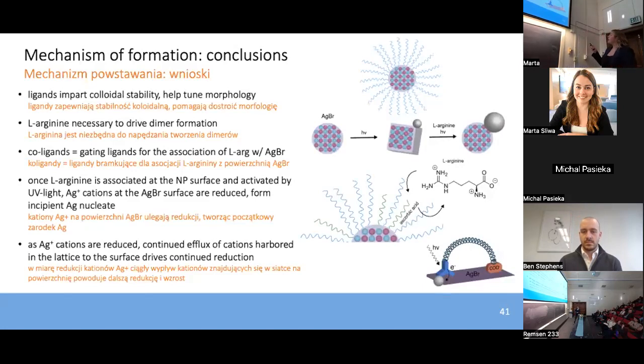Ligand titration studies, again, also indicate that the co-ligands on the surface act as gating ligands for the association of L-arginine. When we introduce L-arginine, it kicks off that gating ligand and is therefore able to associate with the surface. As the L-arginine performs reduction of the silver cations present on the surface of the particle, they start to form an initial precipitate or a nucleate, and as that nucleate continues to grow and silver cations continue to get reduced, there is a continued depletion of the interstitial silver cations from the host lattice to the surface where the L-arginine is, which drives continued growth of that silver phase.